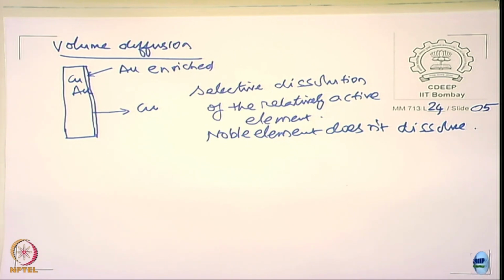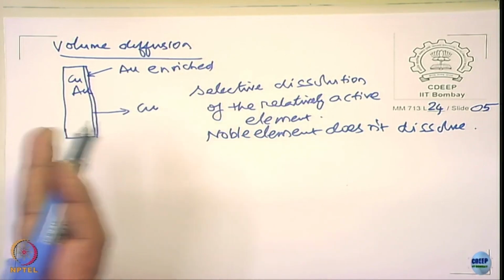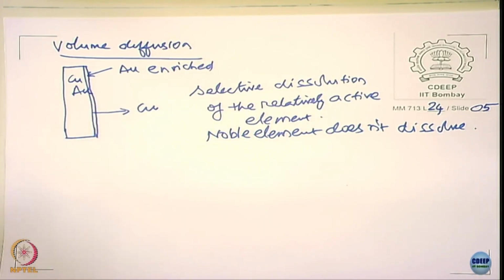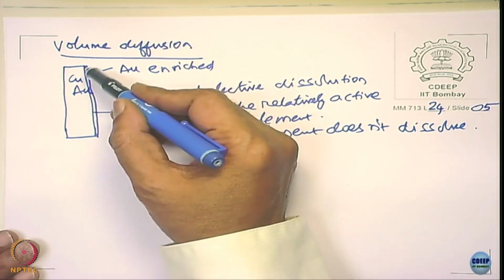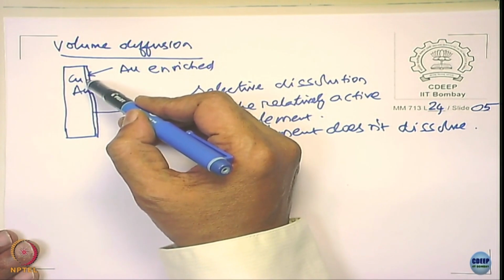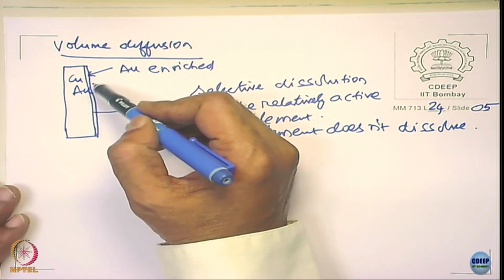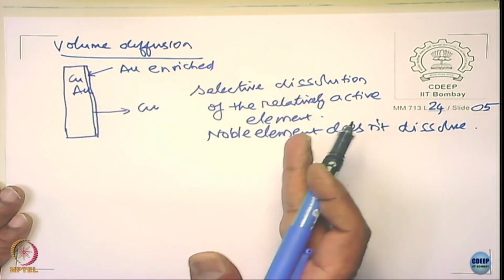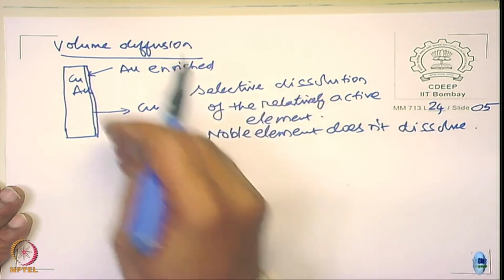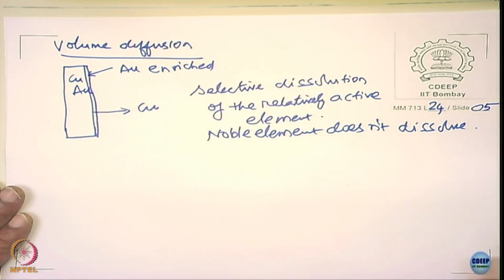And there is a problem here. Can you tell me what is the problem? The problem is that the diffusion of the elements at ambient temperature is so low, right. If this process has to continue, unless the copper comes to the surface, it is not possible for the dealloying to continue, am I right? For the dealloying to continue, the copper from the lattice has to diffuse and then come to the surface, and then only there can be dealloying. If it does not happen, a few atomic layers of the alloy will dissolve where the relatively active metal goes into solution, and then thereafter there will be no dealloying taking place,